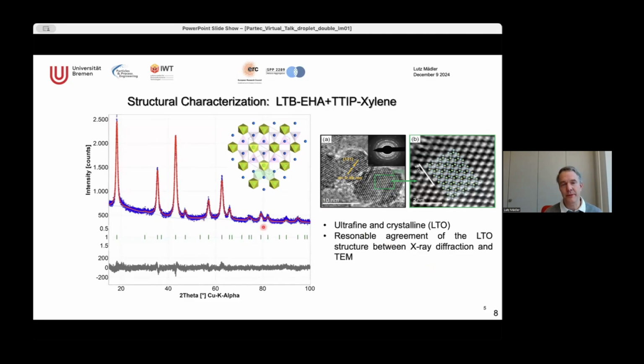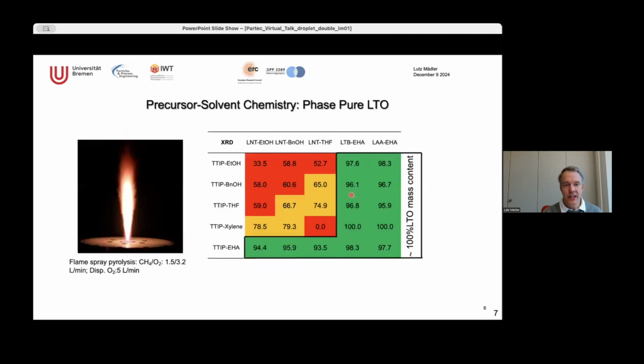We did some Rietveld refinement to find that. And we can also confirm that on some high resolution TEM, where we actually can take that crystal structure from the XRD and check if we really have those crystals also in the TEM. And as you also see, our particles are very crystalline, which is good for many, many applications. But this is not the case for all those precursor solutions. And that's exactly my point.